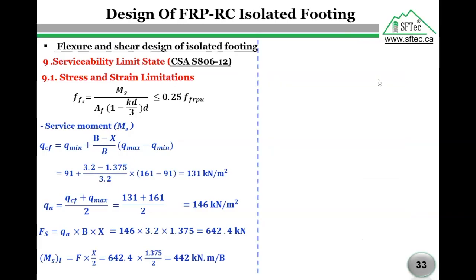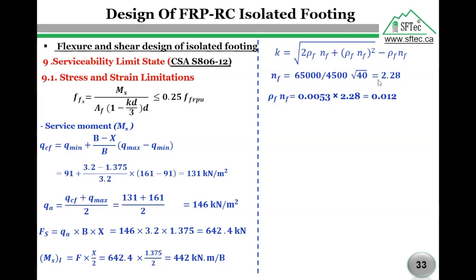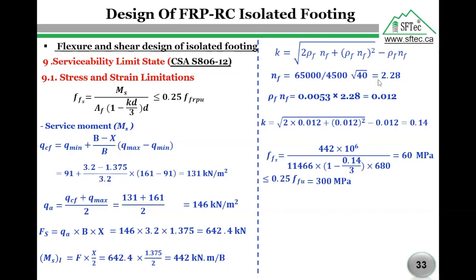So now we calculated Ms and we have the depth of the foundation. So the unknown for us is a factor called k. k can be calculated using this equation, which depends mainly on the flexural reinforcement ratio and the modular ratio, nf. The modular ratio is the ratio between the elastic modulus of the used bar to the elastic modulus of the concrete. So rho f times nf will be 0.012. So finally k equals 0.14. And the stress under full service loads is 60 MPa. By comparing 60 MPa with 25% of the ultimate strength in our bar, we will have a safe design.